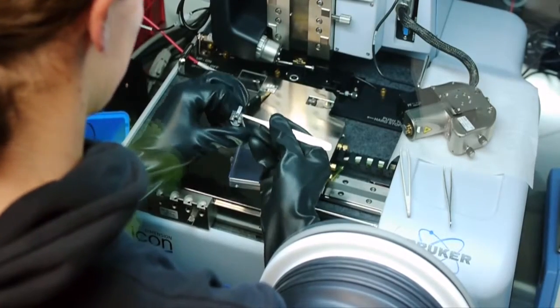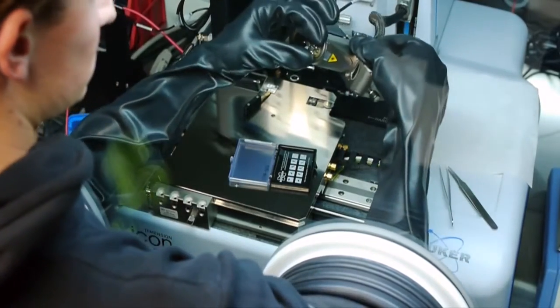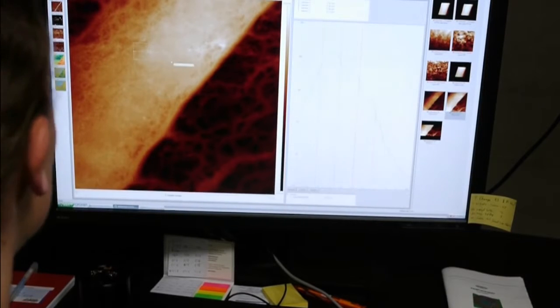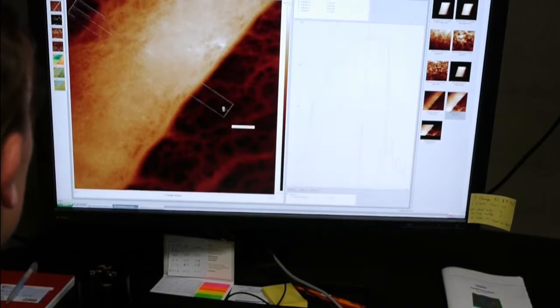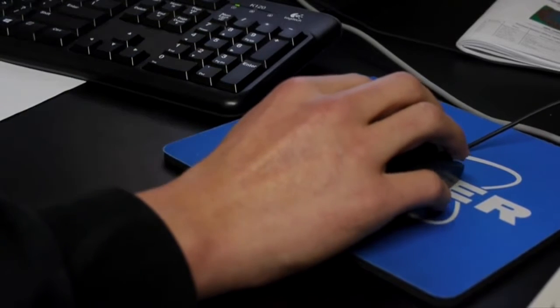Another possibility of locating defects in both solar cells and light-emitting diodes is to examine them under an atomic force microscope in the characterization lab. The organic semiconductor is inserted through an airlock into a glove box. Scientist Stefan Reich installs the probe tip into a holder and aligns the laser. The measurement needle is passed over the surface of the substrate; from the electrostatic interaction between the measuring needle and the surface, the computer calculates the height of the layers, displaying the result as a layer height profile.